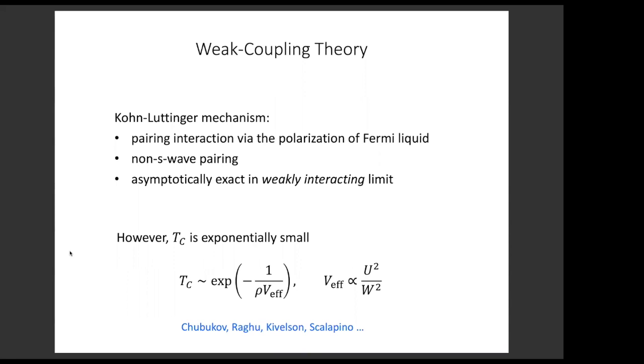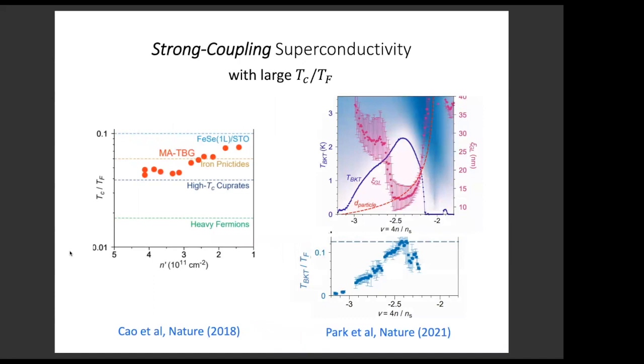Next slide, please. So now, as I already mentioned, superconductivity has been found in many correlated systems, and in particular, these superconducting states seem to be very robust, and the ratio of the transition temperature and the Fermi temperature is substantially higher than in conventional metals. It can reach between 1% to 10% of the Fermi temperature.